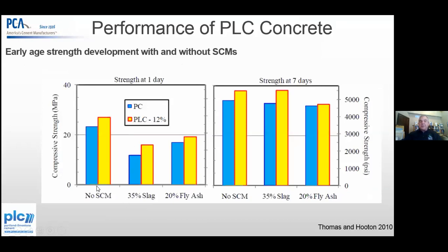So early age development, this is without SCMs. Portland cement is in the blue. Portland limestone cements, and this was a 12% Portland limestone cement content. Without SCMs, it had a little bit higher strength in this particular one. With slag at 35%, it had a little bit better performance, and with fly ash at 20%, a little bit better performance again. 7 days, it carried all the way through.